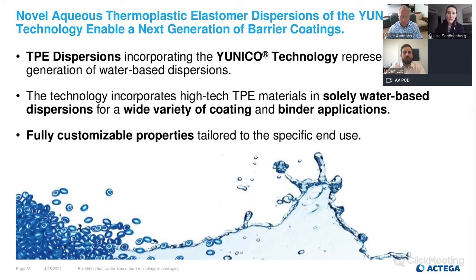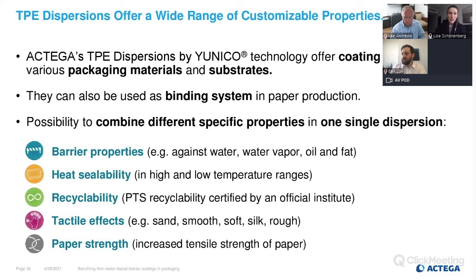And more importantly, the technology allows multiple polymers with the right range of properties to be combined in one single dispersion, and this results in an adjustable multifunctional barrier coating. The customizable structure of the dispersion coatings makes them suitable for a wide variety of coating applications and substrates. So grammatures of the paper materials in current projects range from very thin paper with around 20 grams per square meter to thick cardboard with up to 400 grams per square meter.